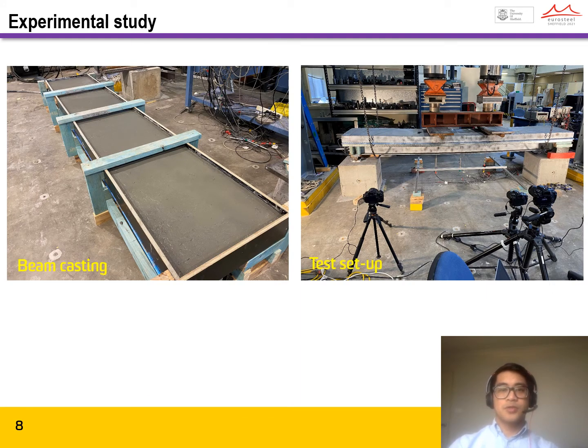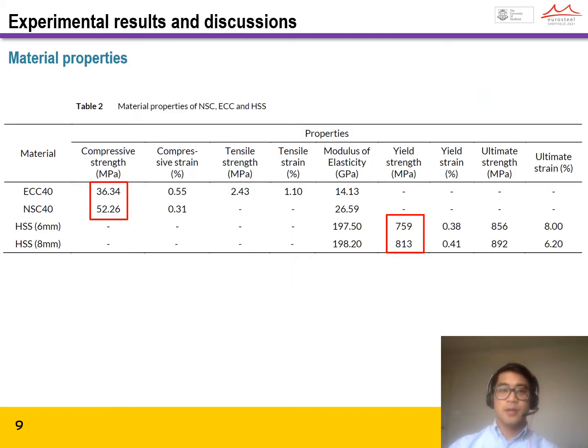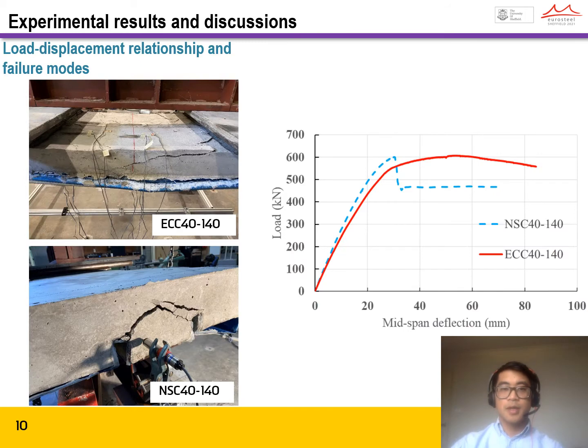The left-hand side picture shows the beam after casting, and the right-hand side shows the test setup. Three cameras were deployed to record crack, strain, and displacement history using digital image correlation. Based on similar tests of ECC and NSC, it can be clearly seen here that the compressive strength of ECC shows a lower value than that of NSC, that is 36 versus 52 megapascals. The minimum yield strength of the high-strength steel was about 750 megapascals. The load displacement relationship of the tested beam is shown in this figure.